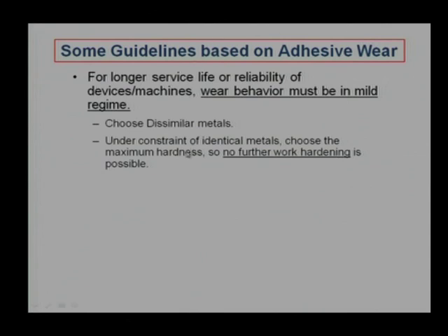Another one says to choose higher hardness. Of course, this does not mean that you go to very high hardness where brittle fracture occurs on its own, like in ceramics. But choose a hardness where further work hardening is not possible. If we reach a level where no further work hardening is possible, that kind of hardness is sufficient to reduce the wear or to bring the components into the mild wear domain. If we follow this, I am sure that component life will increase.